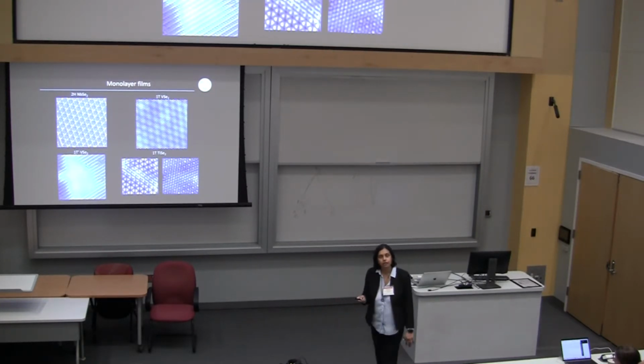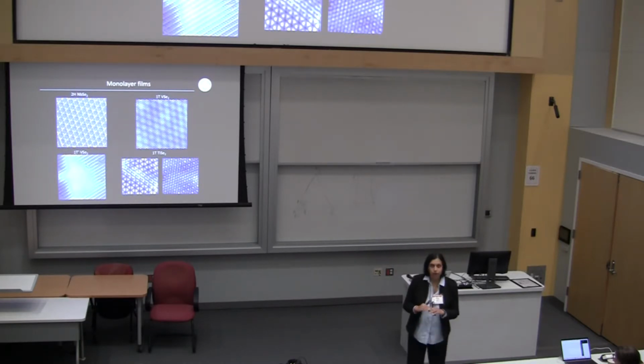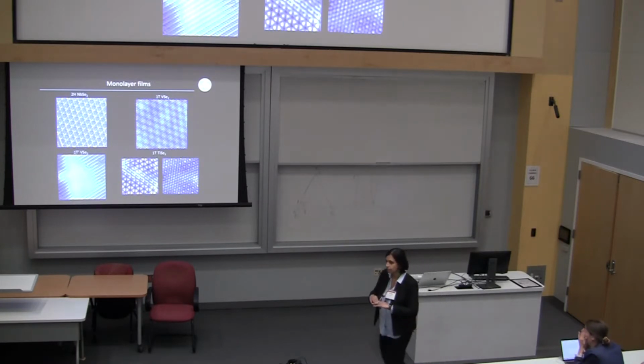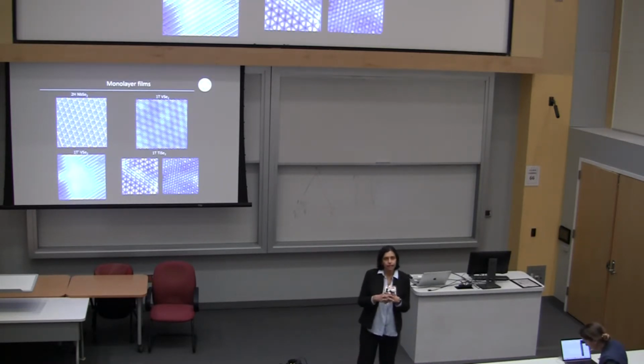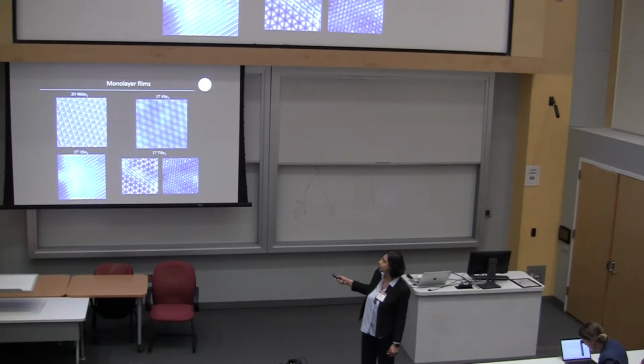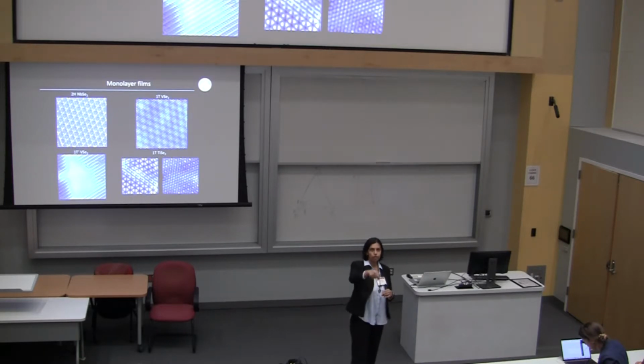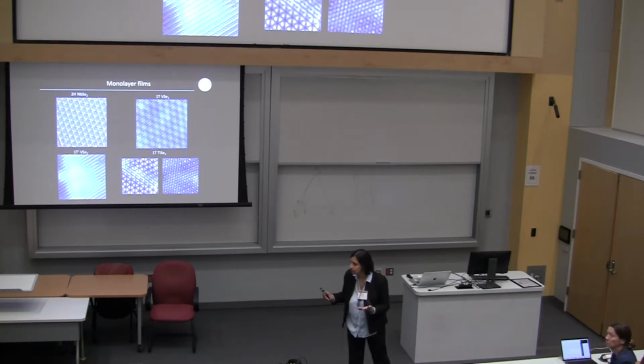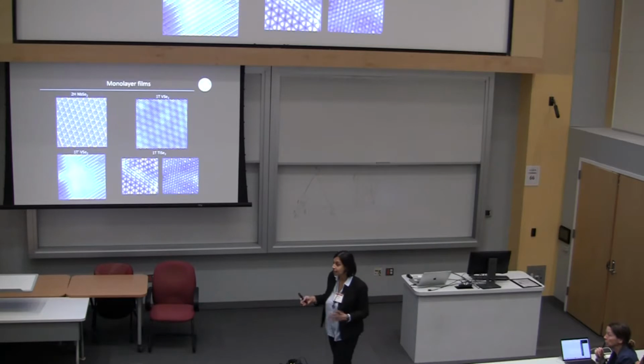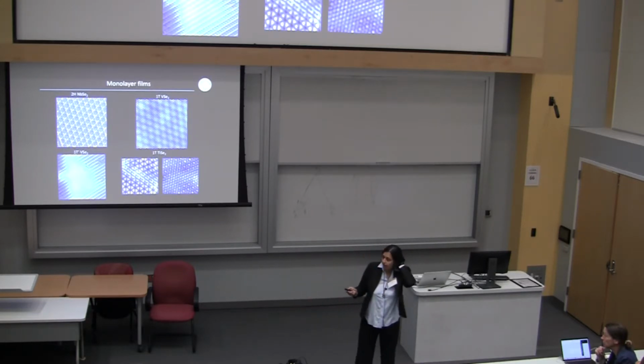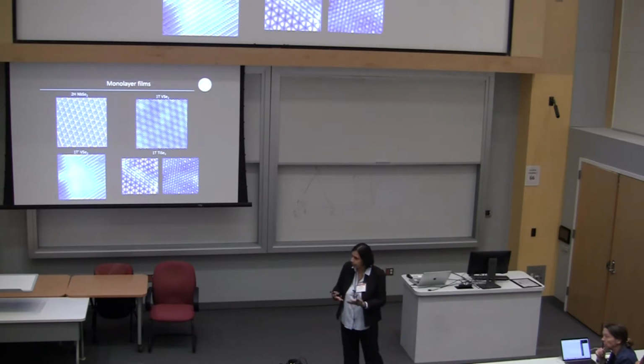So one nice thing about growing on graphene is, I don't know the actual reason for this, the films that we grow on graphene are sort of very decoupled from the substrate. So they're almost like they're floating on top. And I'll tell you why we know this. First, we don't see any strong moire patterns in any of these films, right? And secondly, I'll show you, in fact, for niobium diselenide, I'll show you a spectra taken on the bare graphene substrate and the niobium diselenide. And the graphene doesn't seem to influence the density of states in the niobium diselenide at all. So yeah, I think maybe they just sort of, many people have noticed this.